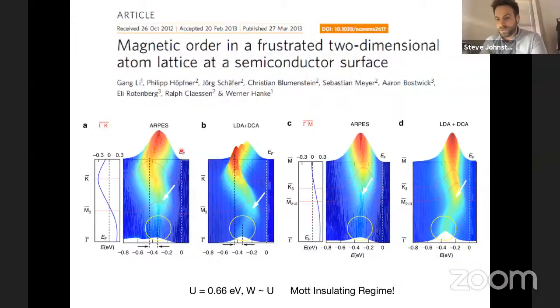This is what we would normally associate with a lower Hubbard band. This persists along both momentum cuts. And then in comparison to this LDA plus DCA calculation, they found that there was really good agreement. And they argued that this was really indicative of a Mott insulator or a Mott insulating phase in the system. They also discuss a little bit of evidence they have for some zone folding here, which they link to magnetism, but I don't want to go into too much detail about that here.